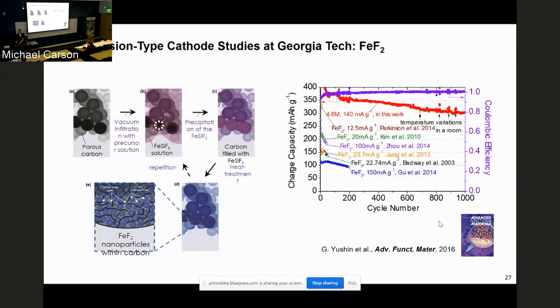And similarly, we demonstrated quite some time ago that by nanostructuring this material, nano-confining it within this matrix, in this case, activated carbon matrix, amorphous carbon matrix, you can achieve significant performance boost. You can achieve longer cycle life. You can get 2 to 3 times higher gravimetric capacity compared to state-of-the-art materials.